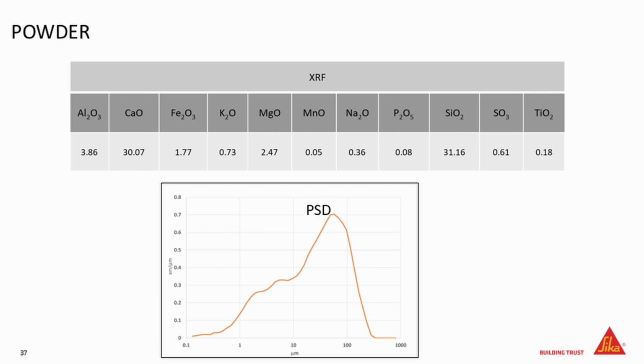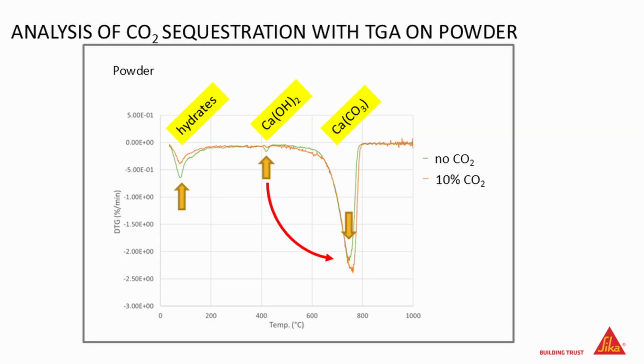One other aspect of separating these two steps, step 1 and step 2, is that when you put in the CO2 and you sequester CO2, you basically have the opportunity to get CO2 certificates for this because you bind CO2. And one key element of this is how to measure the bound CO2. And that is not so easy in the continuous process.